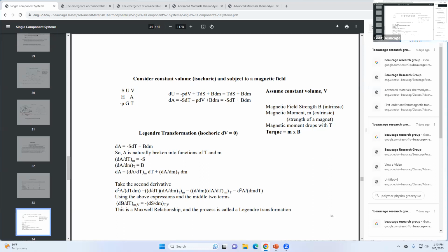So you can measure the field, that's his input, temperature's his input. You can measure the magnetization, then you can get dS if he has this Maxwell relationship. And dS is the thing he wants to quantify where he's getting cooling from his refrigerator, right? Because T dS is going to be the energy that he's absorbing in his refrigerator. So anyway, how do you get that expression? It's a Maxwell expression.